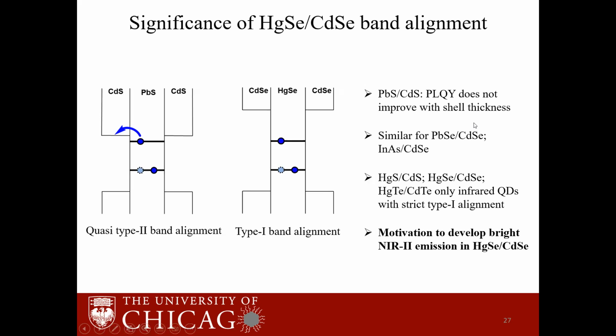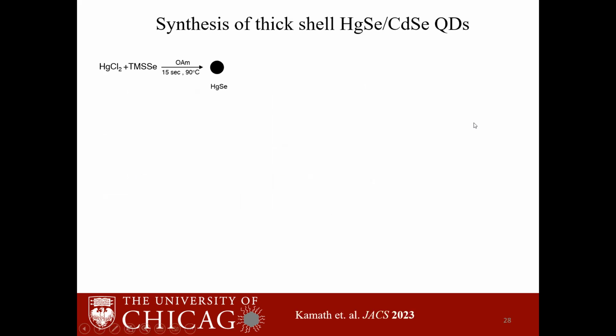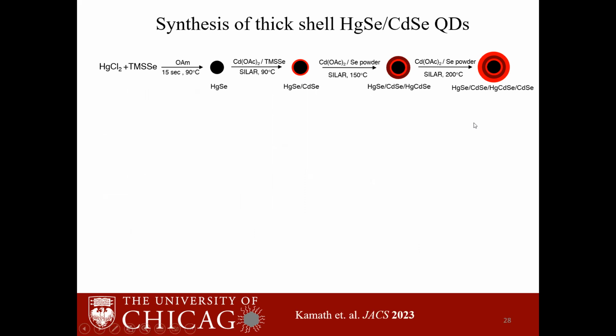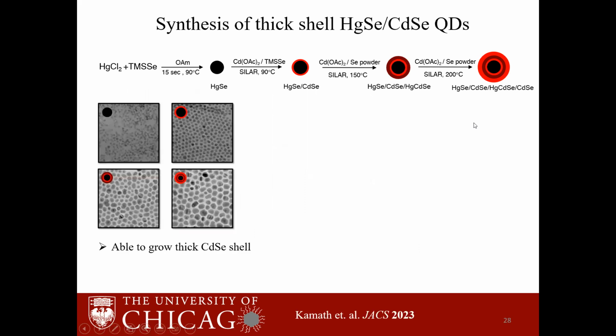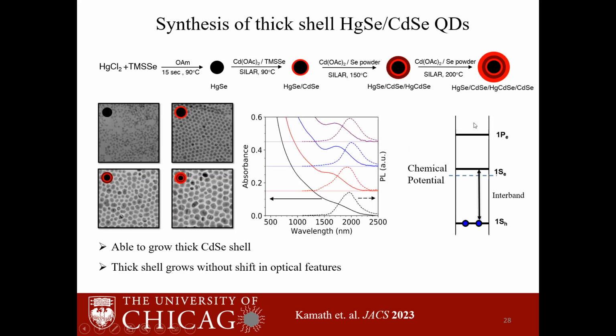So this was our motivation for growing a thick cadmium selenide shell around mercury selenide quantum dots for slowing the non-radiative rate in the shortwave infrared. Similar to our previous work, the first step is to grow a thin interfacial shell to impart thermal stability before we can grow a thicker shell at a higher temperature. Using this method, we were able to grow thick and roughly spherical shells. And as we can see from the absorption and emission spectra, the peak positions do not change with the shell thickness. This is a further confirmation of the type 1 band alignment between mercury selenide and cadmium selenide.